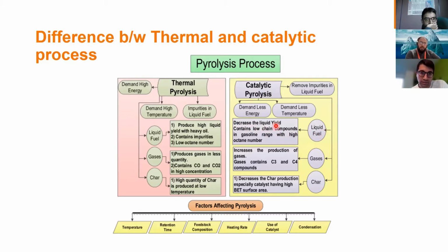And if you look at the products from the pyrolysis, then the liquid yield is basically decreased, because the gases are increased. You have more cracking, you have more gases, but at the same time, the quality of the liquid is improved, because you have a more narrow range of hydrocarbons in the liquid fraction. The gases that are produced from catalytic pyrolysis contain a lot of C3 and C4s, valuable compounds. In the catalytic pyrolysis, the char production is decreased, especially with catalysts having high BET surface area.